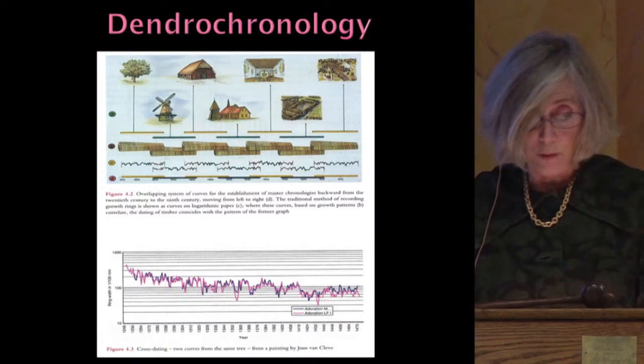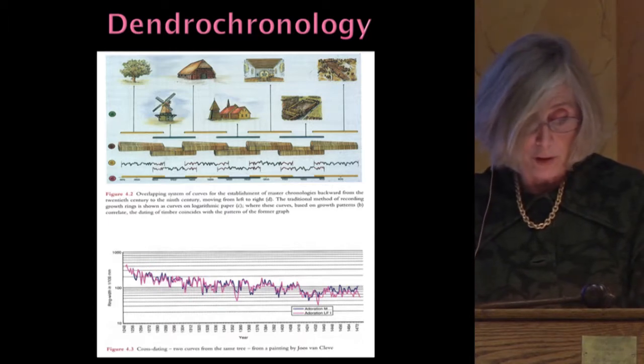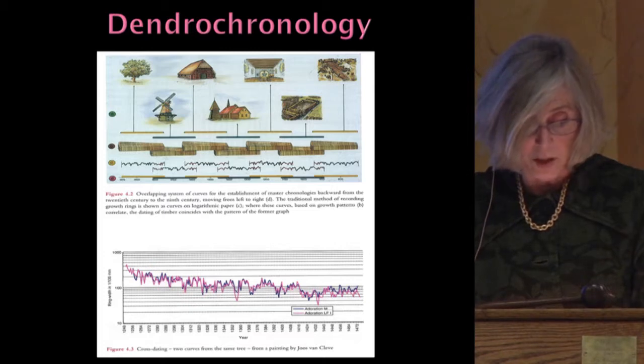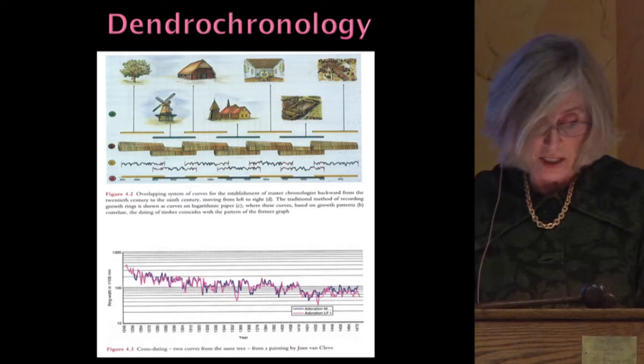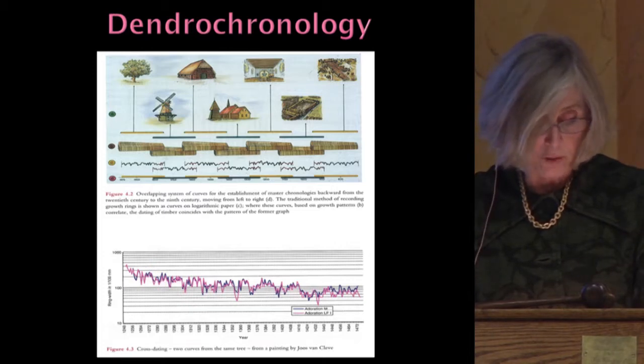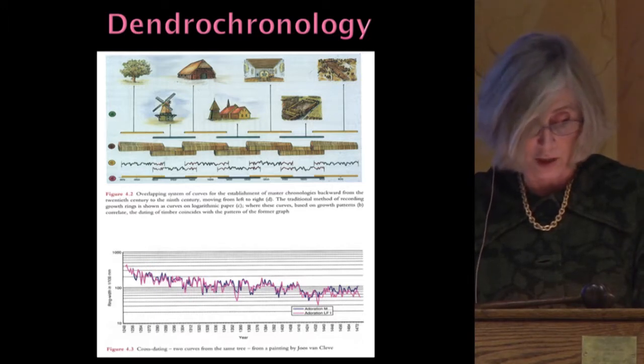Dendrochronology, used to date wood panel supports, is another valuable tool. The goal is to offer an earliest possible date for a painting based on the felling date for the tree. The dating is based on the biological regularity of the ring series in trees from temperate zones, comparing the ring sequences of undated wood with those of wood of known age and position in time. There are separate chronologies from a variety of regions, all of which are mapped in an overlapping system of individual curves for the establishment of master chronologies.